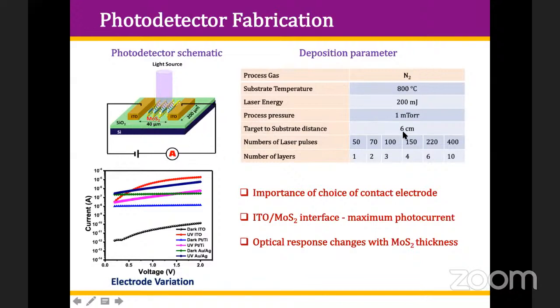These are the deposition parameters which we optimized. We fixed the temperature at 800 degrees, and then changed the number of laser pulses from 50 to 400 to make 1 layer, 2 layer, 3 layer, and 10 layer of MoS2. I mentioned in the beginning that the contact electrode is very crucial, so we tried gold, silver, platinum, titanium, and ITO as the electrode. If you see the dark current for the ITO is this, and the photocurrent for ITO is this orange one, and a very large change in the current is observed with the ITO. So ITO seems to be the best electrode as far as UV photodetector application is concerned.